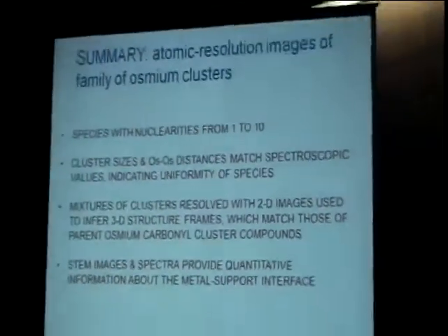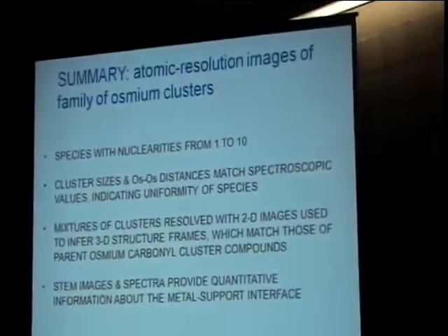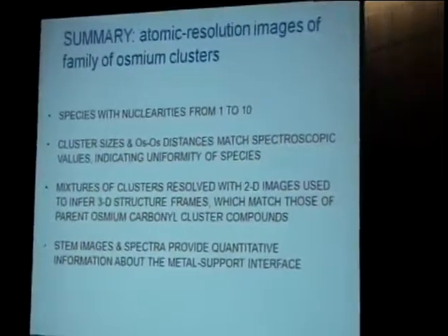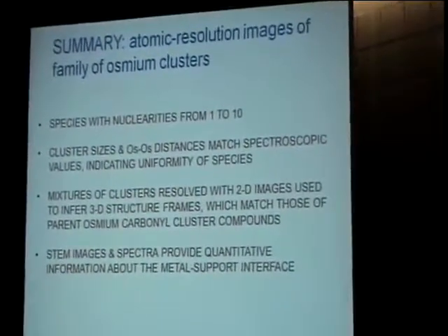And also the assumption, which seems to be consistent with all the data, that the metal frames have structures that match those of the parent compounds. Pure compounds with known crystal structures, which are osmium carbonyls, like the Os10C(CO)24 2-. That's, you might say, fortuitous, or we might say we chose a good research direction to get into this field. The bottom line importance is that not only can we get quantitative structural information about the supported metal species, we can get information that's also quantitative about the metal support interface structure, and that requires using spectroscopy in combination with microscopy.